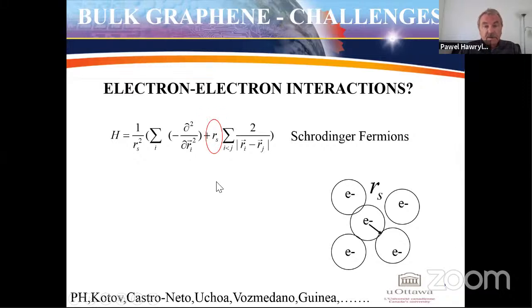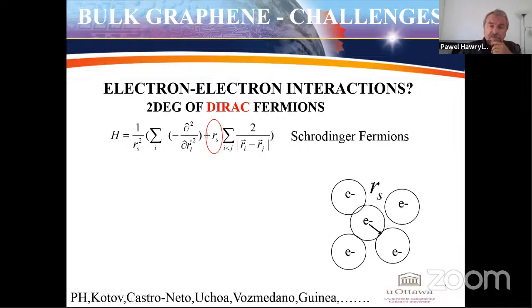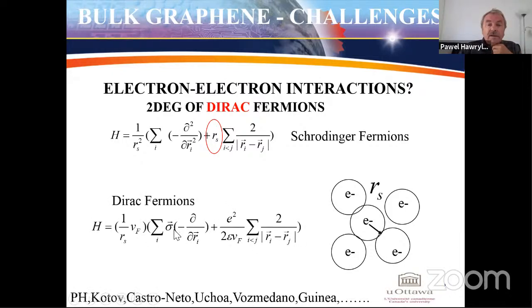However, yes, so this is the Rs. However, if we look at the two-dimensional gas of Dirac fermions, then we have linear dispersion. And so this parameter that controls the ratio of Coulomb energy to kinetic energy does not depend on density, but it depends on the Fermi velocity and the screening provided by the surrounding material. So it does not depend on density. We are ignorant, for any density, about the properties of this material.